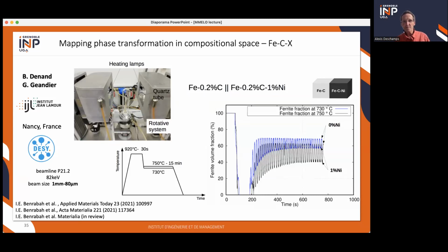The sample is a cylinder sitting here. It's heated by heating lamps, and actually this part is rotating at about 5 to 10 hertz. And the rotation helps to get powder conditions for diffraction, because then you can probe all orientations. Well, not all, but many orientations. And you can get quasi-continuous Debye-Scherrer rings and have much more quantitative data.